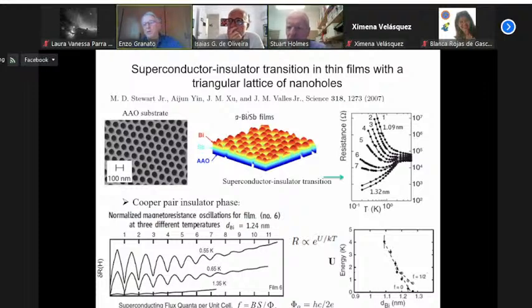Every time you have a multiply connected superconductor, like a ring of superconductor, you have a flux that's one integer flux, you repeat because of 2 pi. But in this fractional oscillation that you don't see here in this particular system, but you see in the others, then you need to take into account that there are many vortices, and the vortices cannot fit in the pinning center. Whenever they don't fit, you have a different local minimum and so on.